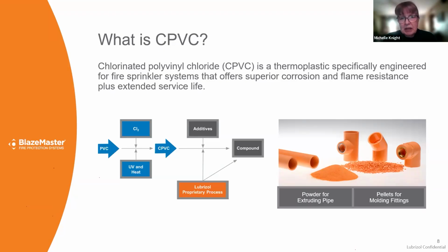CPVC is chlorinated polyvinyl chloride. So we start with PVC and we add additional chlorine to it. PVC is already 57% by weight chlorine. We increase that using UV and heat to catalyze the reaction. We add more chlorine to it, and that gives it higher temperature resistance, better flame and smoke resistance.